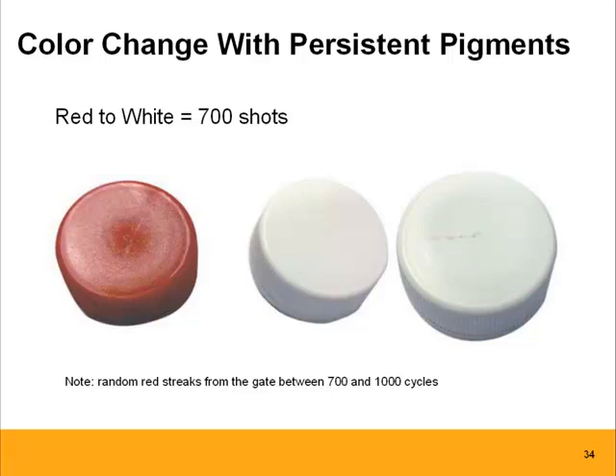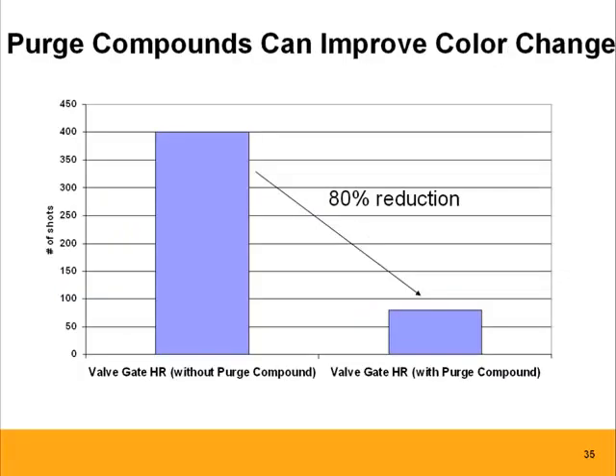So one way of getting around this is using purge compounds. We don't recommend purge compounds for every color change. We don't think it's necessary. But from a planning process, if you know which colors take longer, and if you have cases where it takes really long, like 700, 800 shots to go from one color to the next, a purge compound is a very good alternative from a process point of view that you can introduce in your factory. And again, depending on the application, we have seen up to 80% reduction by using a purge compound when it comes to color changeovers.